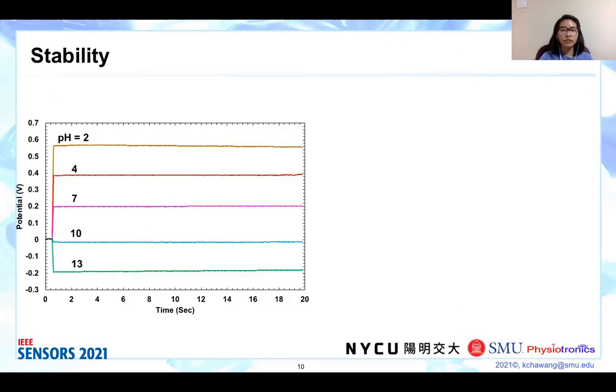Now, potential drift. It is likely caused by ionic diffusion at the liquid junction potential of the electrode. In a timeline of 20 seconds, drift is investigated. Drift at pH 2 is 46.5 millivolt, at pH 4 is 35.2 millivolt, at pH 7 is 19 millivolt, at pH 10 is 20.4 millivolt, at pH 13 is 41.4 millivolt.